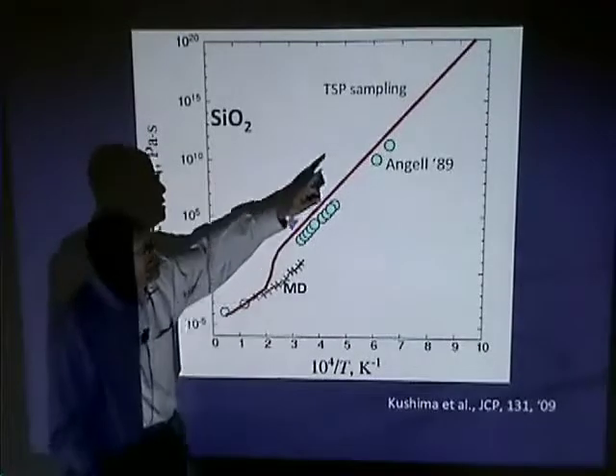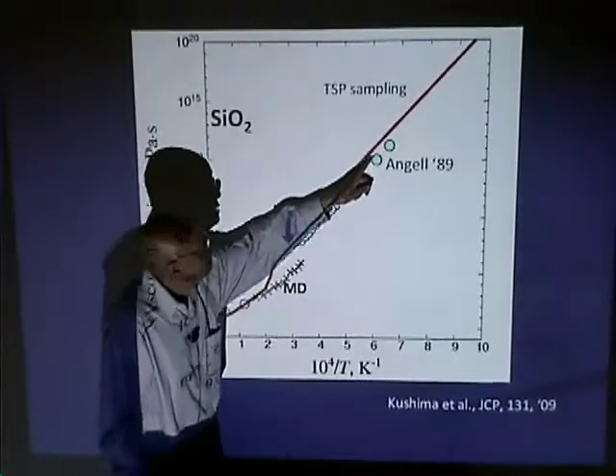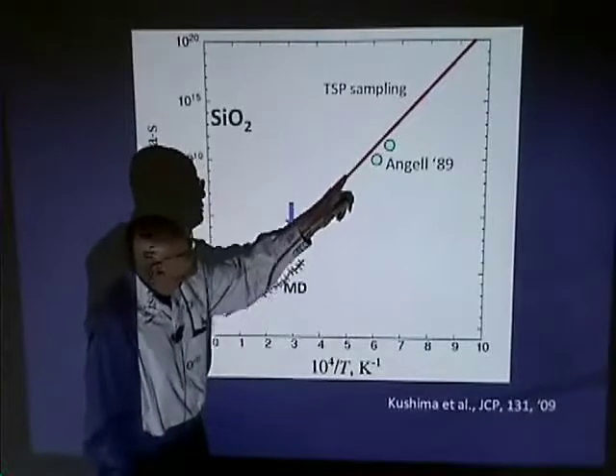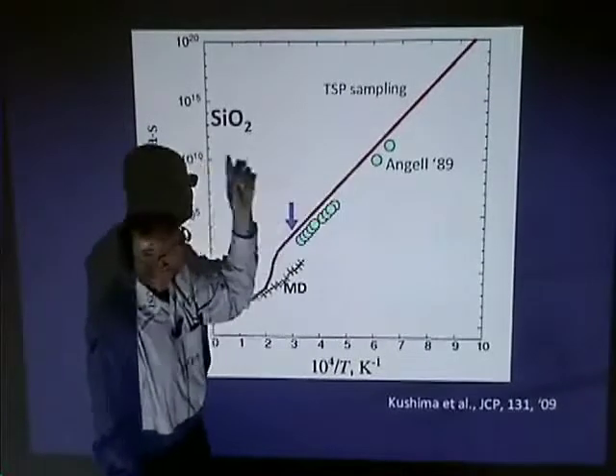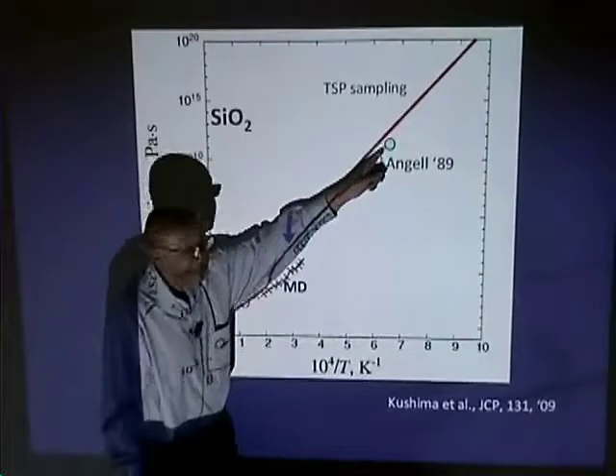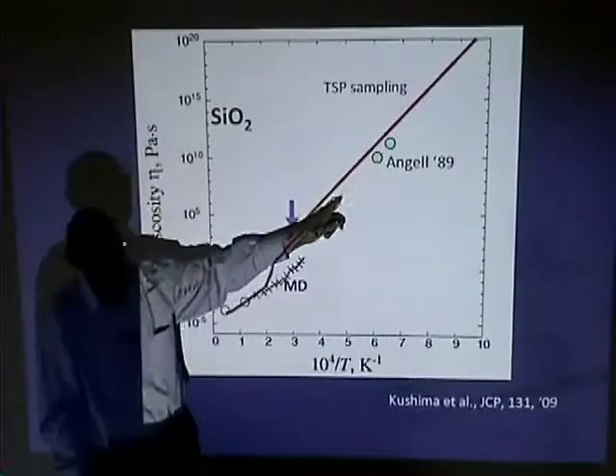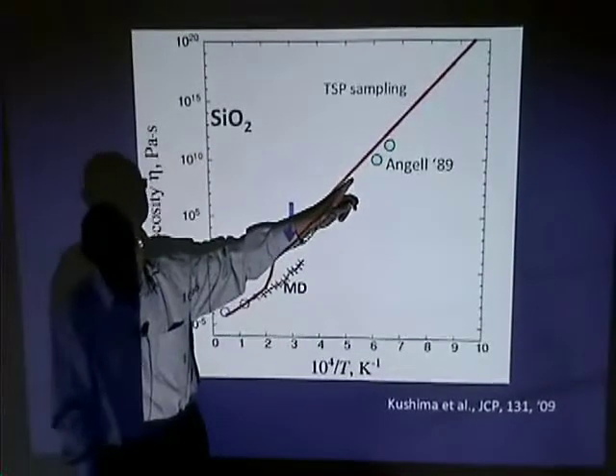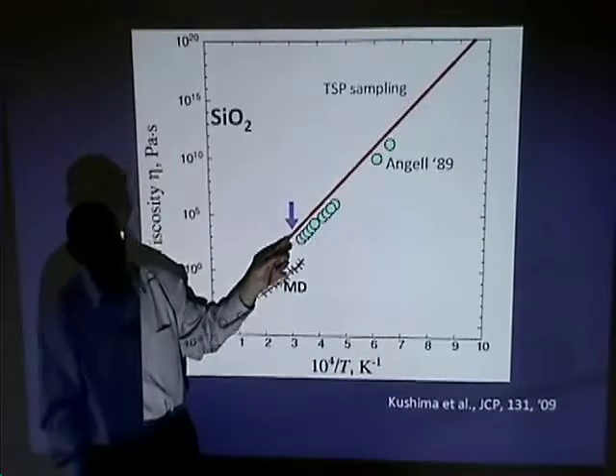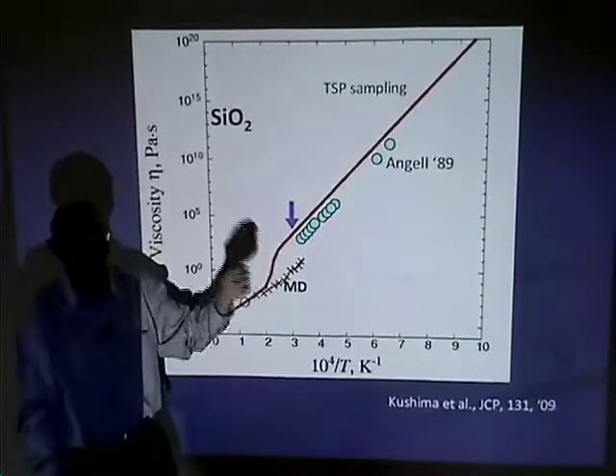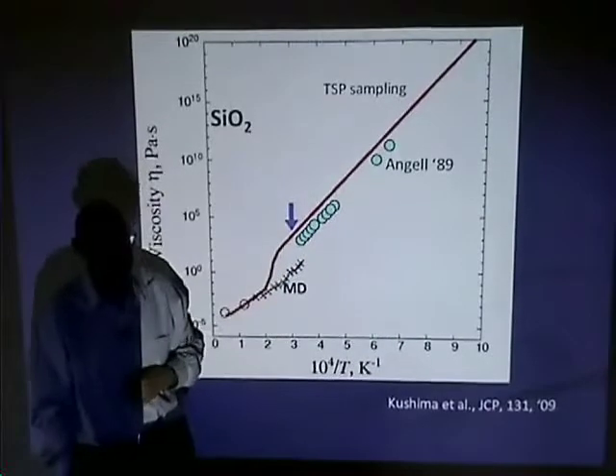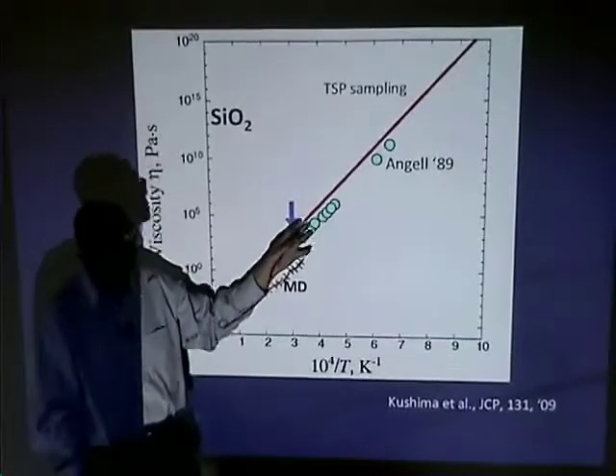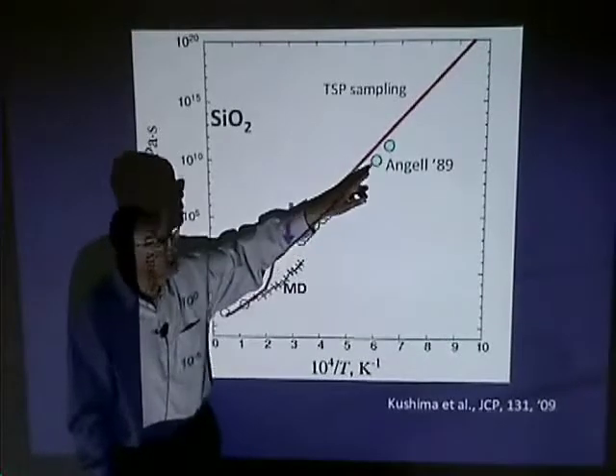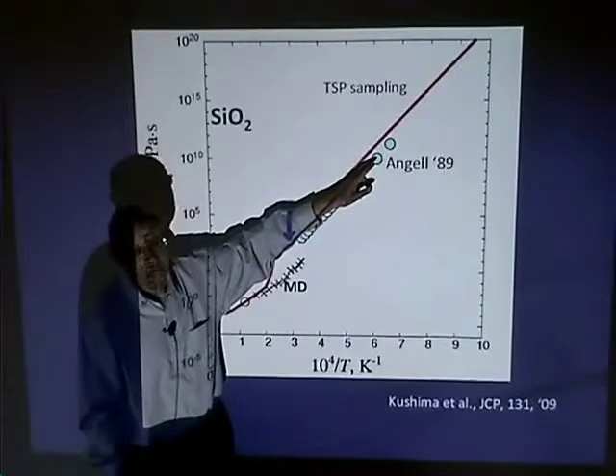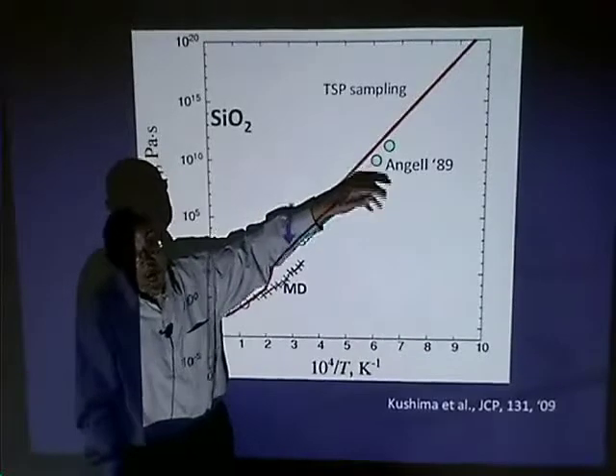But we already can tell the red curve overestimates. Since this is a log plot, there's actually significant consistent overestimate. We understand this, because this heuristic argument is meant to be an overestimate, like an upper bound estimation. So we have physical reasons for expecting that the data should lie to the right of this curve, and this is indeed what happened.